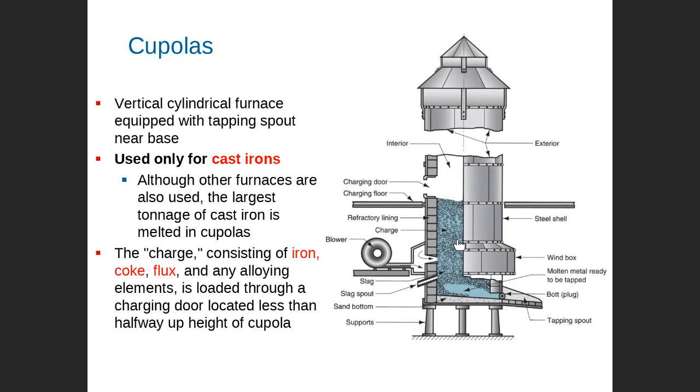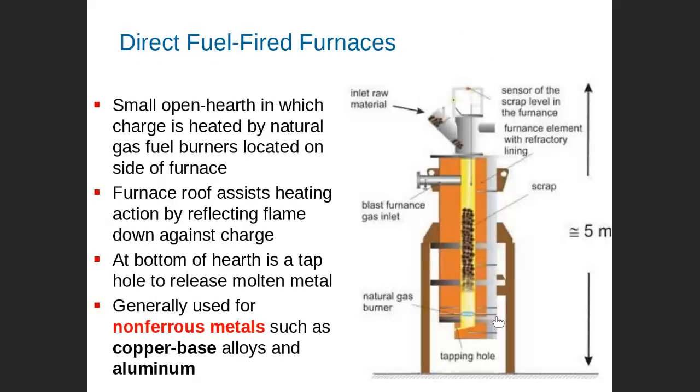When it becomes liquid, this will be trapped inside and will be very difficult to deal with, and become impurity. But in the case of cast iron, no issue, because cast iron is mainly carbon. So if this gets trapped inside, meaning the carbon percent will increase, then no issues. So this one is mainly used only for cast iron, right? We cannot use this with other materials.